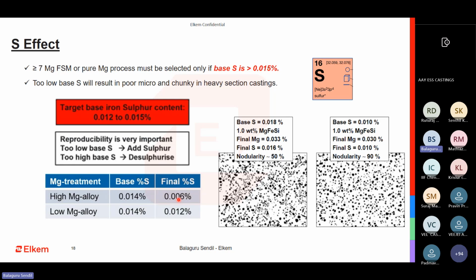So that is why when you are having higher amounts of magnesium, FSM with high magnesium, and you keep using it at higher addition rate, then your base metal will eventually lose sulfur. When you have very low sulfur, then that is also a very tricky problem you will face. You will end up getting full amounts of chunky graphite. You will end up getting exploded graphite. These sort of problems will come. So it is always better to have a correct range of sulfur.